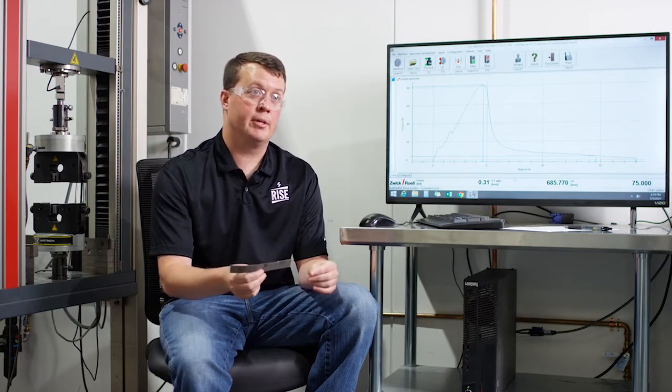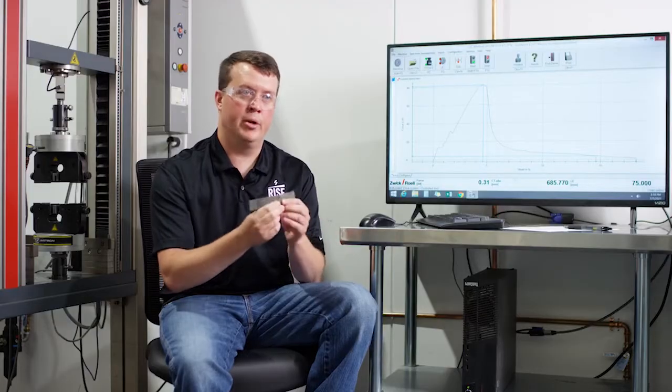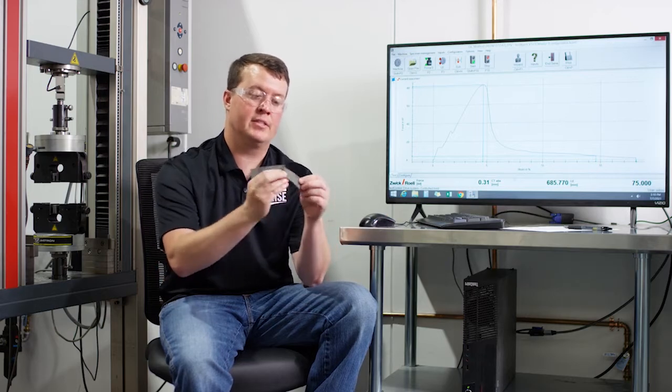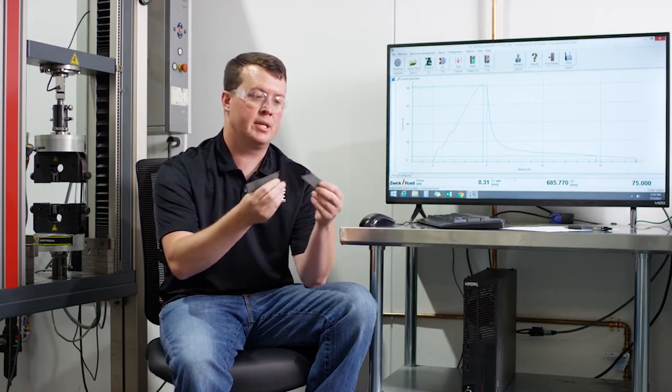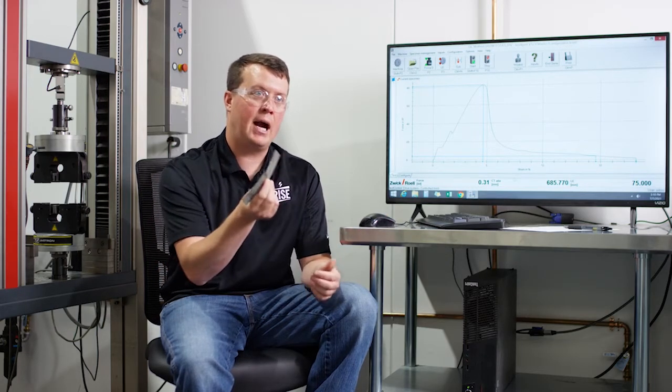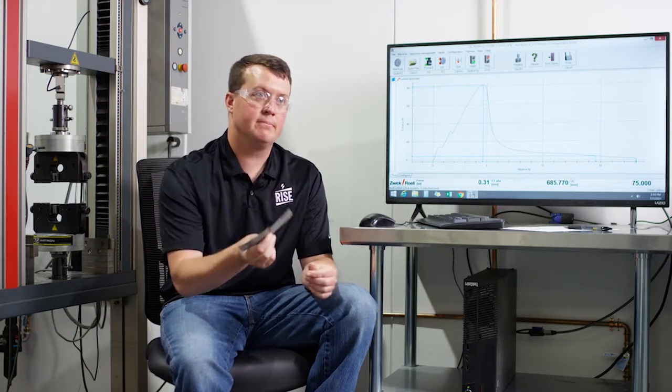The more filler you have in your blend, when you go above 30%, when you go above 40% filler, you've essentially gone from an elastic membrane to more of a plastic. So you're going to have a more rigid membrane. You can kind of see that in this product itself. It's a lot more rigid. It's not as flexible, and that's because it has a higher filler content.